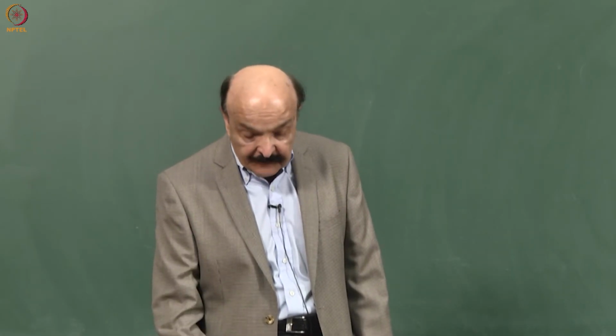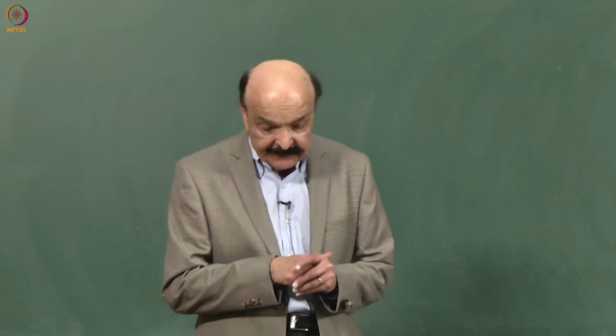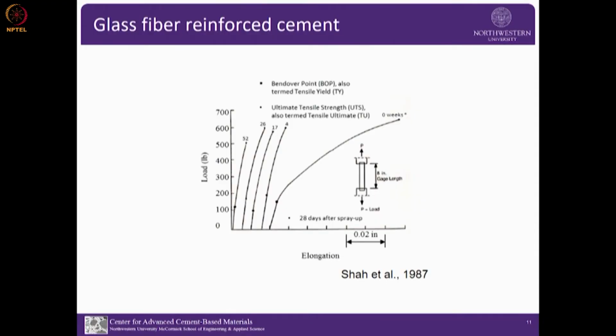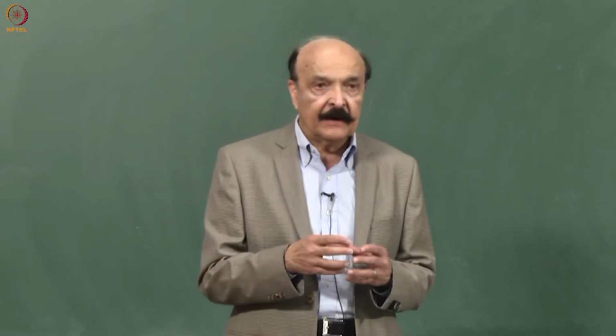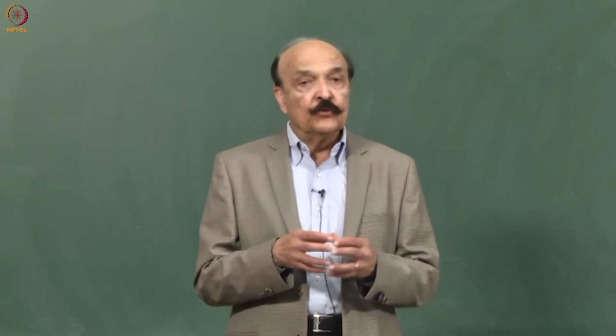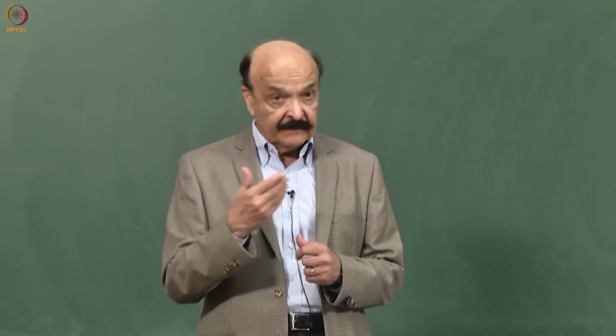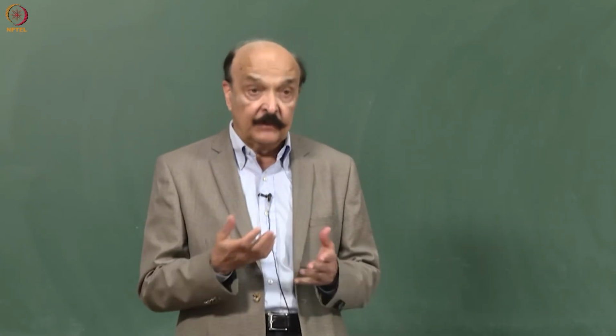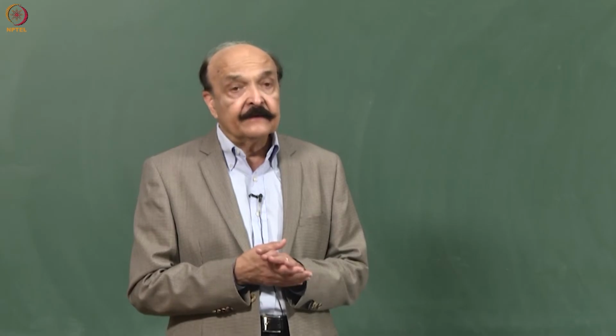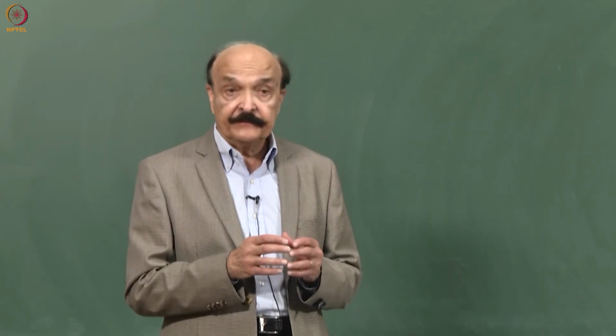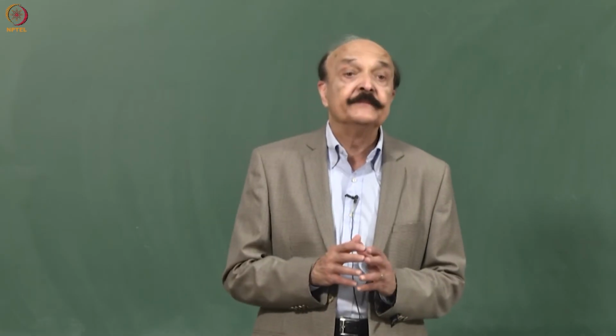And let me show you some work we did with the GFRC. When the alkali resistant glass fiber was developed, to test that it doesn't corrode in the high pH, they do a test with a glass strand surrounded by high calcium hydroxide solution, and then measure the tensile strength with the accelerated test. It's called SIC, and they showed that alkali resistant glass fiber in this test works very well.